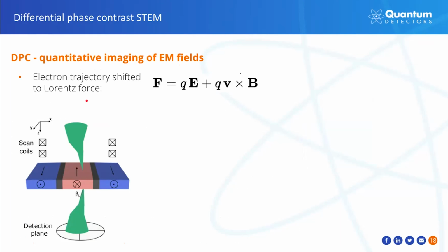So I mentioned previously that MerlinEM was able to improve the speed of magnetic imaging in STEM. This method, called differential phase contrast, can quantitatively measure electromagnetic fields in the sample. It has a small caveat, and that is that the objective lens of the microscope needs to be most of the time switched off, which affects the resolution. The objective lens would otherwise saturate most of the magnetic samples, and no internal fields would be present to image.